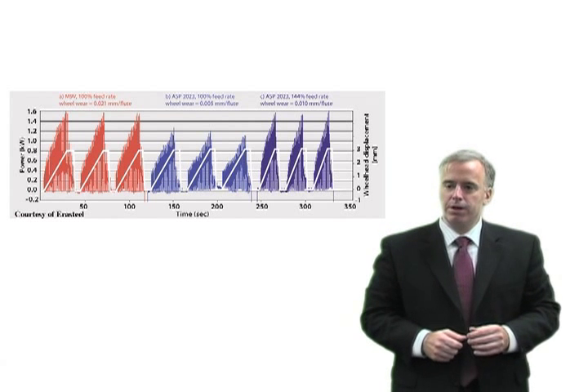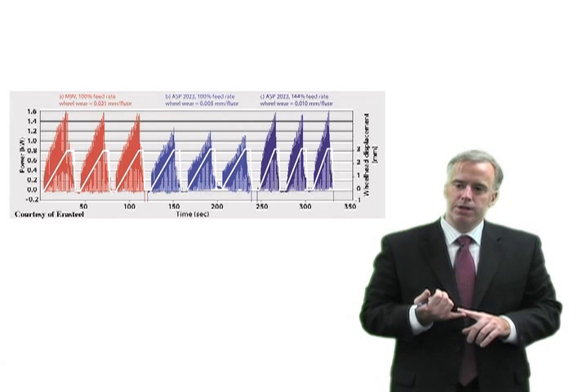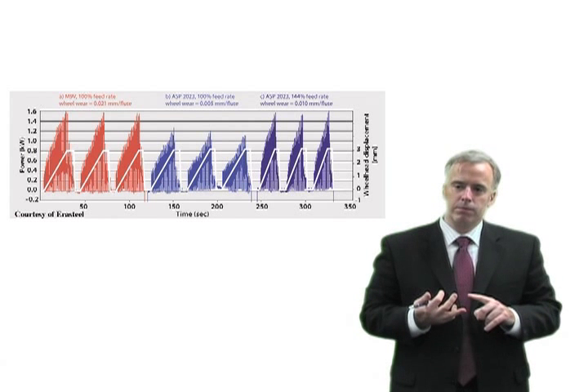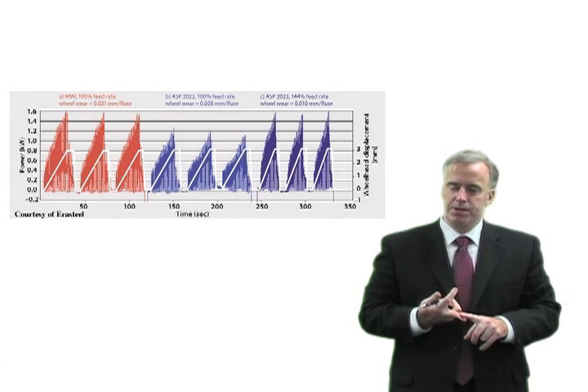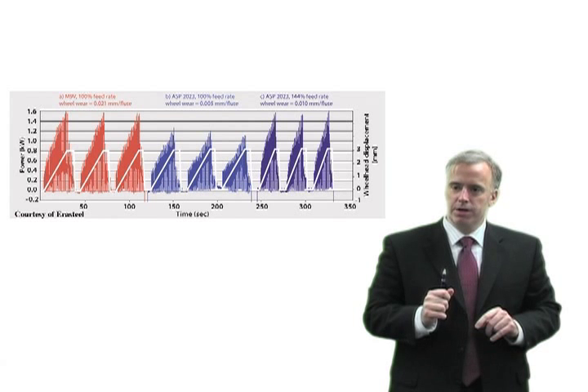They have much lower grindability, and that's going to result in more wheel wear, more heat generation, and in order to compensate for that, you're going to have to slow down your feed rates.